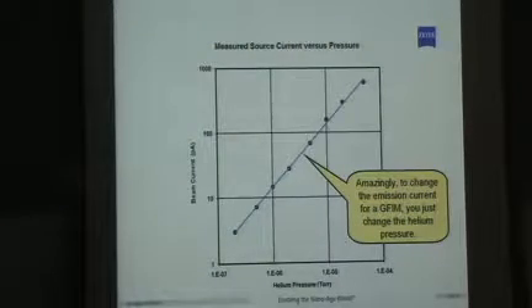One of the neat things about this ion source is if you take a look at the beam current on the vertical axis and the helium pressure on the horizontal axis, you'll find that it's perfectly linear. These are one at a time events. So if I want more current, I can add more helium. If I want less current, I can add less helium. So a leak valve actually lets you explore about 6 orders of magnitude in beam current. That's a dynamic range that's very hard to explore in a SEM or a gallium source.